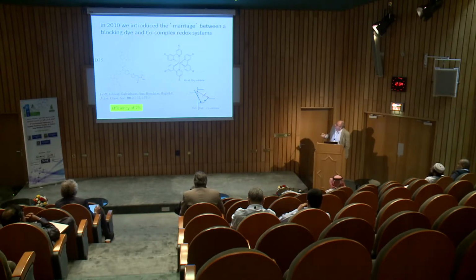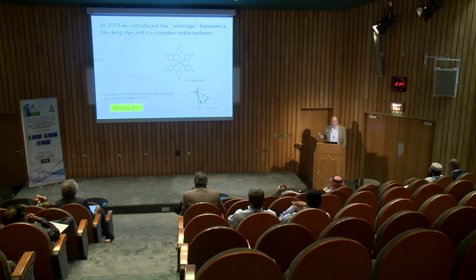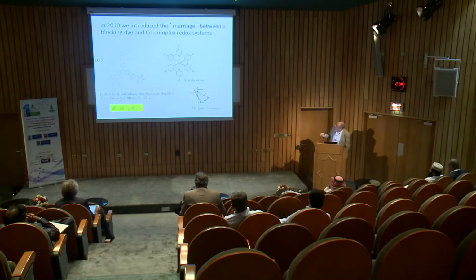This was successful. They do not aggregate because of these groups, but we had an unexpected, I would say, luck here, and that was that with these alkoxy groups we can also passivate the recombination process. As I said, normally we are worried about electrons in TiO2 reacting with the electrolyte in such a process, but with these alkoxy ligands here we could stop that and passivate that reaction, and that was not intentional, but we had a piece of luck.